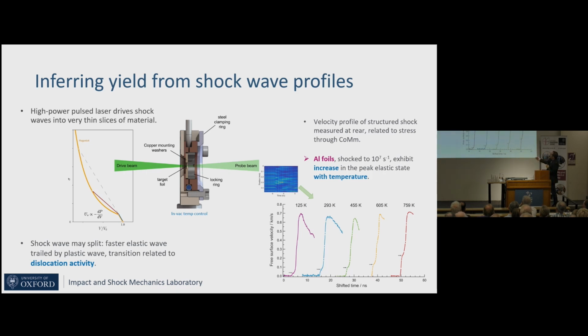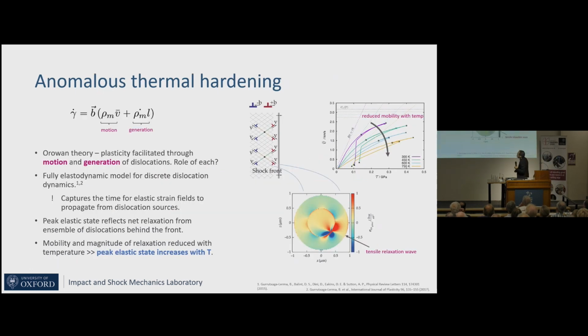Now, what might surprise you is that I'm increasing the temperature in this. This is aluminium. And as I increase the temperature, conventional wisdom would say it should get softer. But it gets harder. It doesn't just get harder. It gets harder by orders of magnitude. So that's really surprising. So we had some thoughts, and we had a very talented then student, now associate professor over at Birmingham, who put together one of the first fully elastodynamic models for dislocation dynamics.